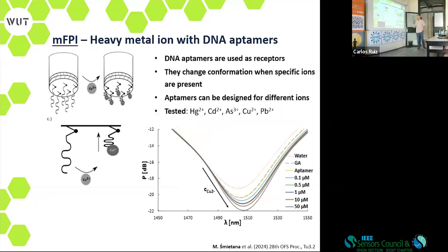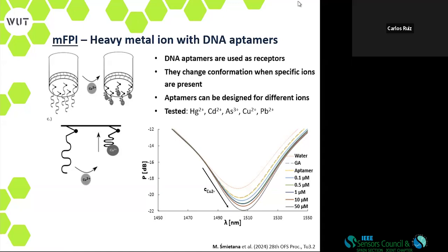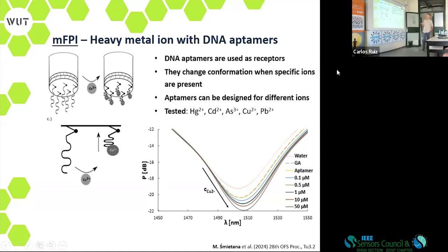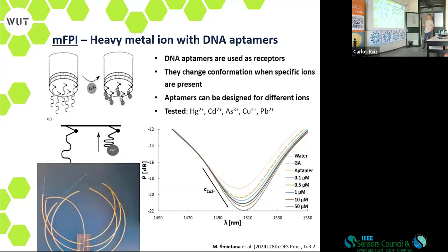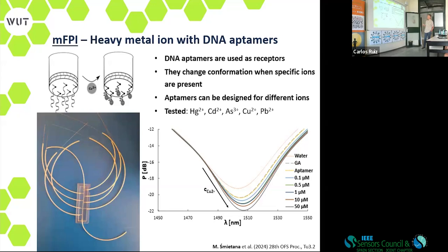And the other application of that is heavy metal ion detection. So we functionalize the surface of this very simple structure with aptamers, DNA aptamers. These are chains of nucleotides, and they change their orientation, they coil with presence of certain ions. So you can see that the mass is getting closer to the surface when the ions are present. And we see that with the concentration of copper ions, the depth of this minimum changes, and also it shifts in wavelength. And we try different heavy metal ions in this configuration. So right now we work on this microfluidic system just to detect many ions at the same time.